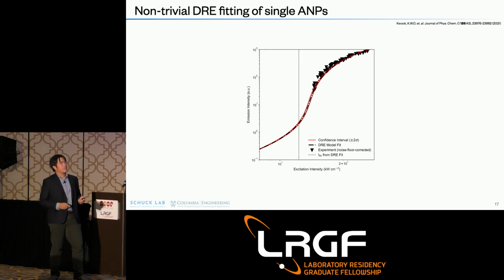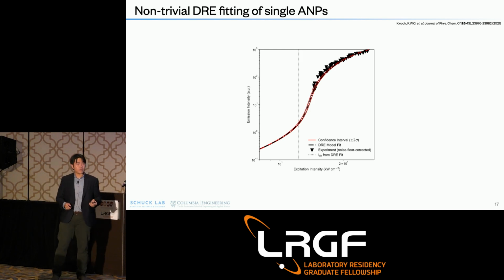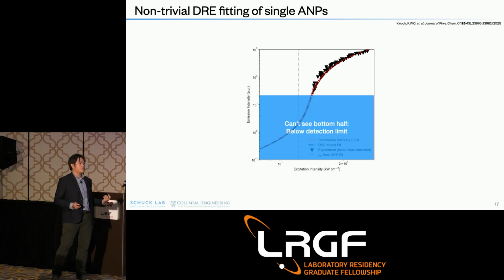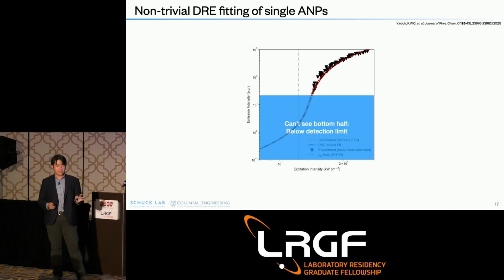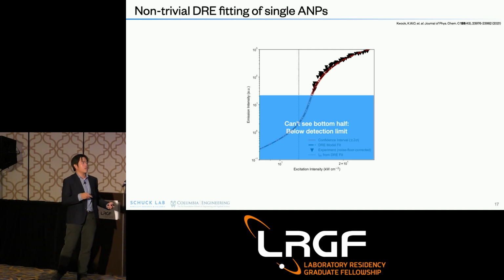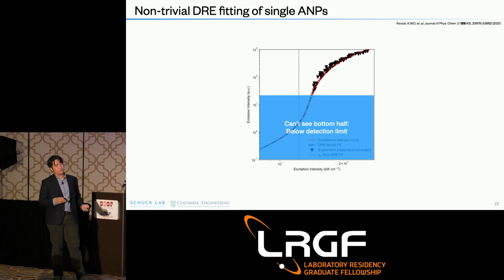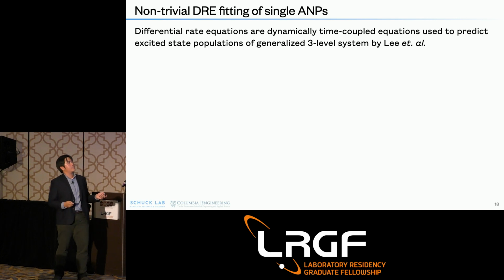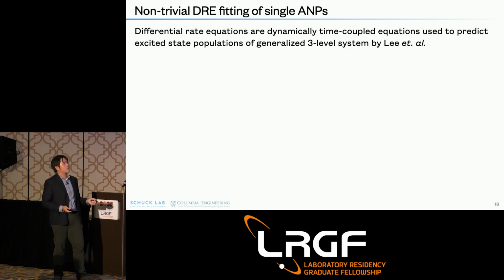Now, single ANPs behave very differently from ensemble ANPs. What's disappointing is that when you're looking at a single ANP, you have a lot fewer emitters, so your detection efficiency is effectively lower, and we can't really see the bottom half of the S-curve itself. So what we relied on is the DRE model. It's called the differential rate equation model.